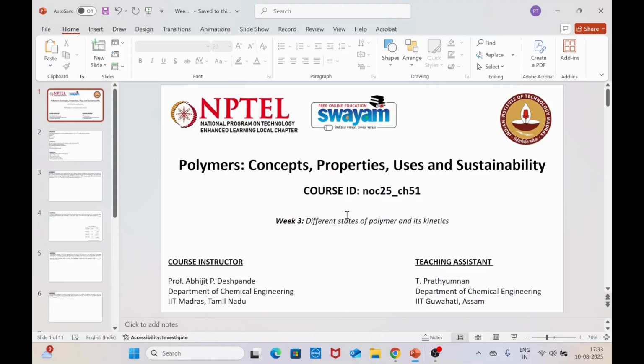The next one is cross-linking. If the polymer system which is given to you has a lot of cross-linking, then folding will also be very difficult because of the rigid interlocking of the bonds. That is another reason why cross-linked polymers are typically amorphous in nature. And in the case of copolymers as well as blends, it is also typically not possible to crystallize,